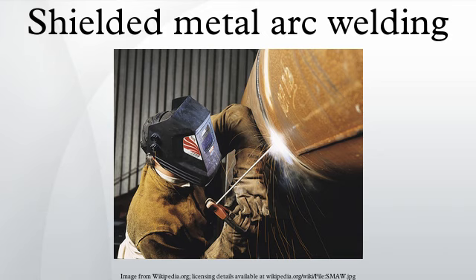Arc blow can also cause porosity in the weld, as can joint contamination, high welding speed, and a long welding arc, especially when low hydrogen electrodes are used. Porosity, often not visible without the use of advanced non-destructive testing methods, is a serious concern because it can potentially weaken the weld. Another defect affecting the strength of the weld is poor fusion, though it is often easily visible.